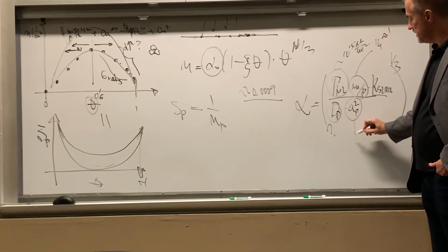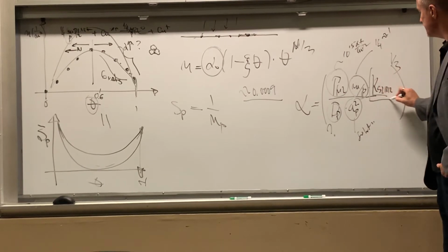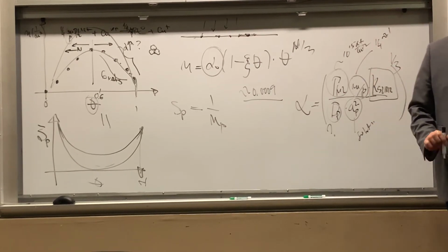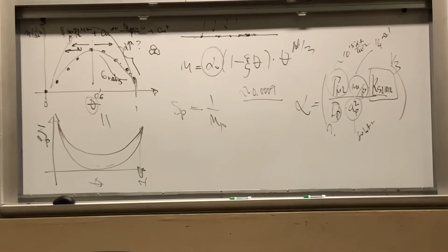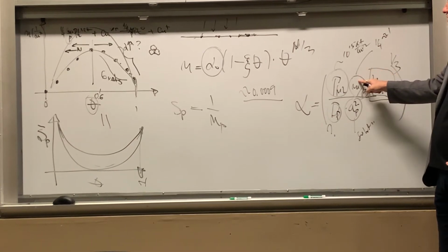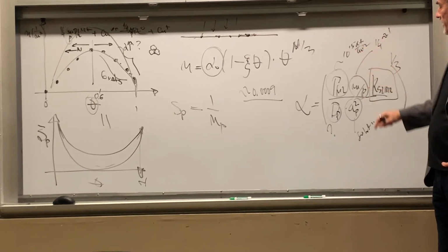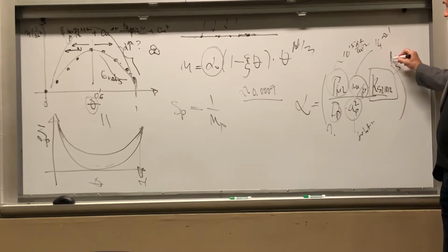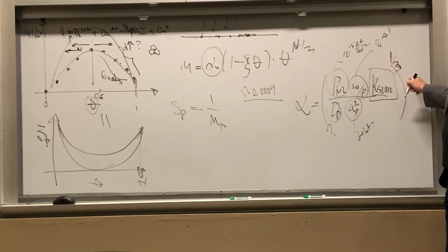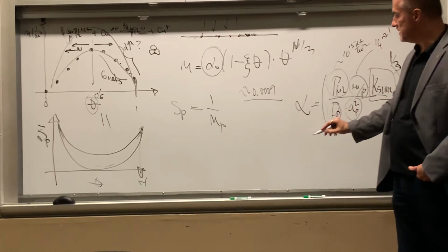And this is related to the substrate, so not much you can do. And this is the K, the constant related to the rate of your reaction. Okay? So I can do something about this, and something about this, which is also tied to N. But since this is a 1/3, which means a third root, whatever I do here, if you think about increasing something 10 times,